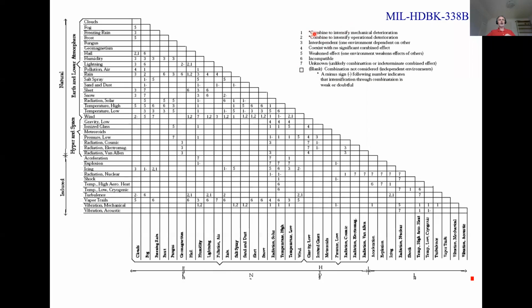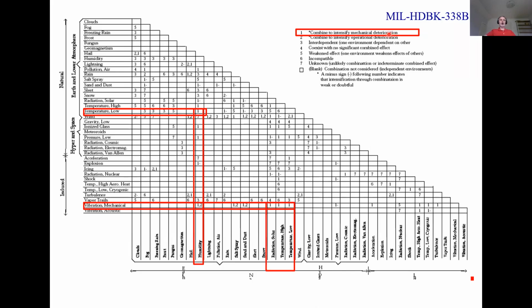So if you see number 1, then it's combined to intensify the mechanical deterioration. So basically, if you have these 2 stresses at the same time, then it means that mechanically the effect is more than 1 plus 1. So let's say low temperature and high humidity, then the mechanical strength is less, because when you go below zero, you get ice formation. Ice causes huge stresses, which can cause cracks, and then your system is mechanically weaker. Another thing could be mechanical vibration and then solar radiation, meaning that, for example, with organic materials, the UV coming from the sun is breaking the polymer chains, or the bonds between the polymer chains.